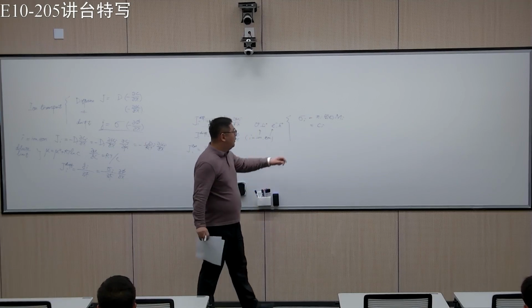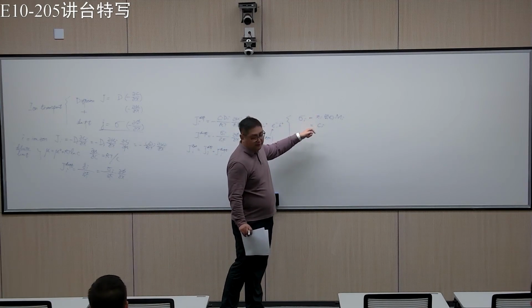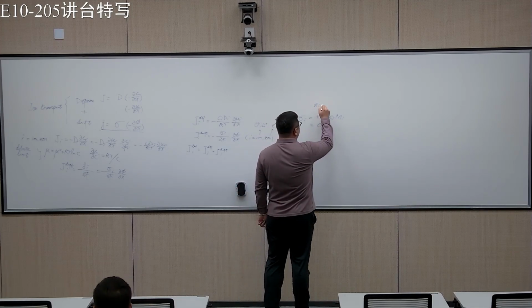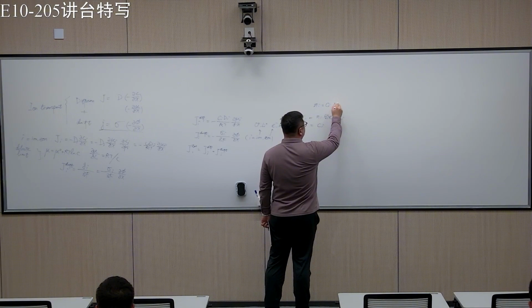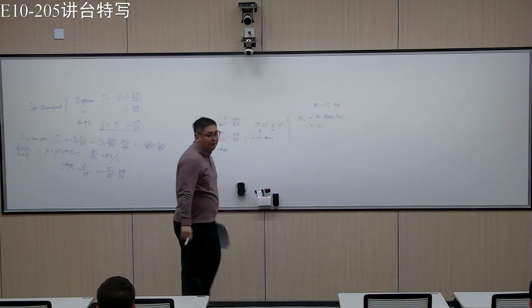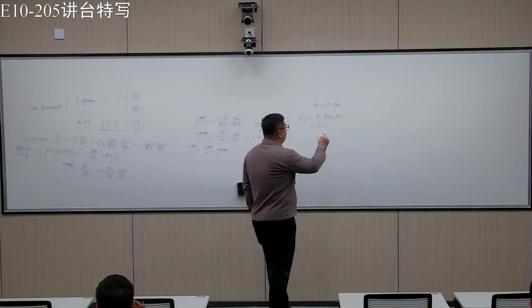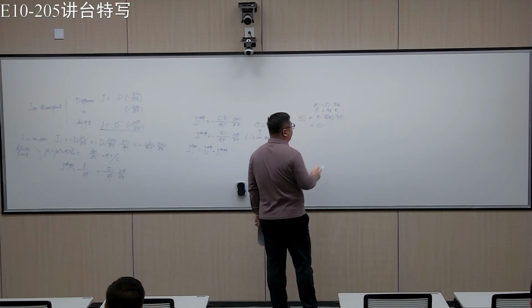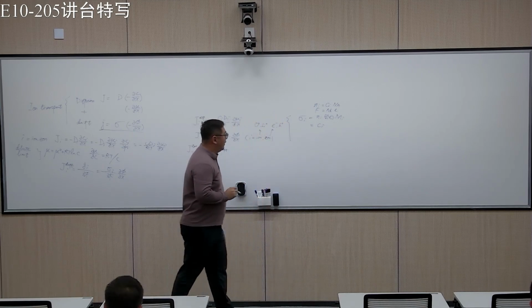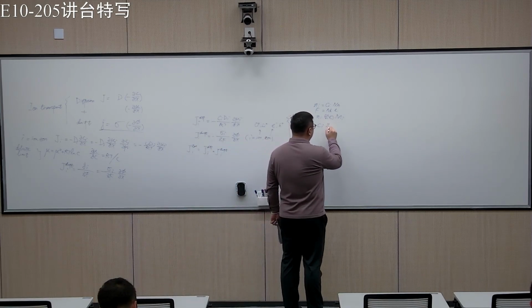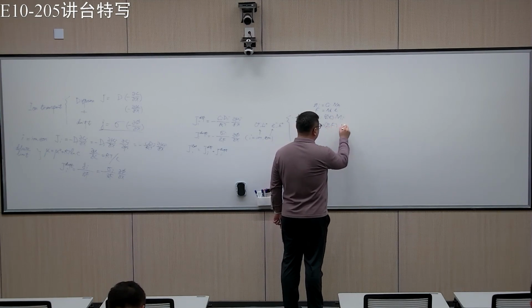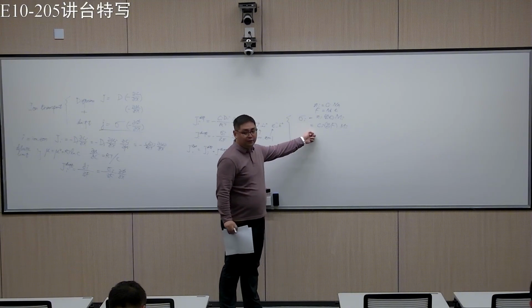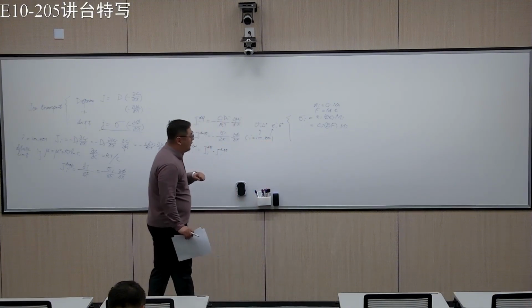Okay. If we change from this one to this one, you basically divide by Avogadro constant. So basically, the number of particles is concentration times Avogadro constant. Okay. Then if we multiply NA with the charge, we get the Faraday constant. So then we can write it something like this. So this is basically what we usually use for conductivity. Okay. So this is the first equation.